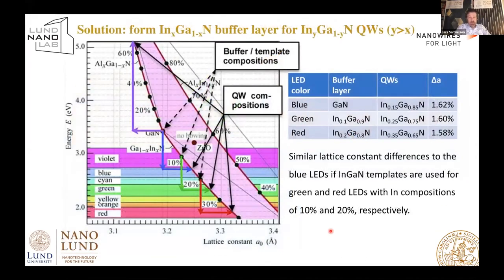So here is what we've been working on for the last 5 years. I think I used this sketch when I applied to the Swedish Research Council 5 or 6 years ago. It's another rather busy slide. What you see here is the band gap energy of the three nitride materials. And here you see the lattice constant, 3.1, 3.2, 3.3, 3.4 angstrom. And you have somewhere left of the center the gallium nitride point here. So if you go in this direction, you're adding more and more indium. And if you follow it all the way down, you're going to get to indium nitride, only 0.7 electron volt band gap.